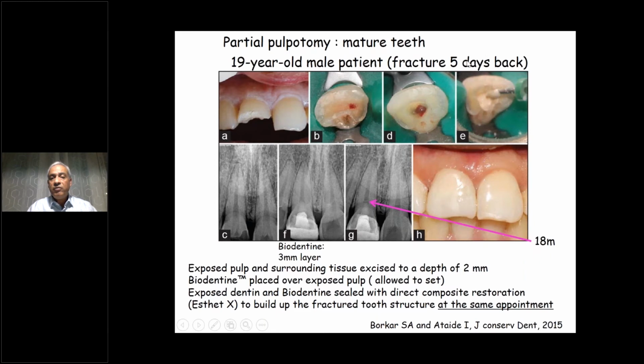That was four clinical cases, tooth fracture, between 5 and 90 days back. I know that for many of you, if it is over 24 hours, you take the pulp out. But here they did another thing: they excised the tissue to a depth of 2 millimeters, then placed Biodentine over it, and built the structure at the same appointment. And look, this is Biodentine, and here the dentin bridge, which formed after 18 months.